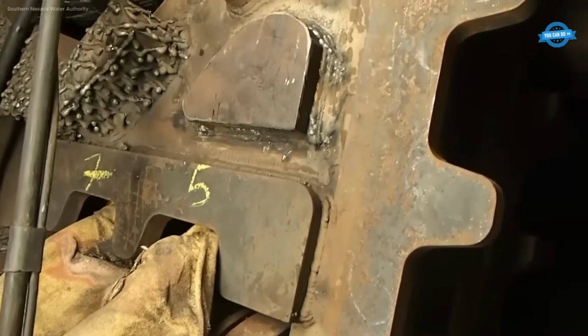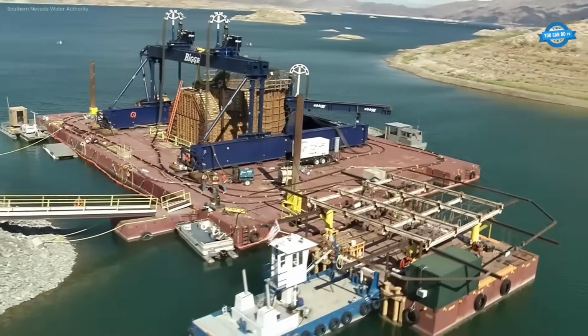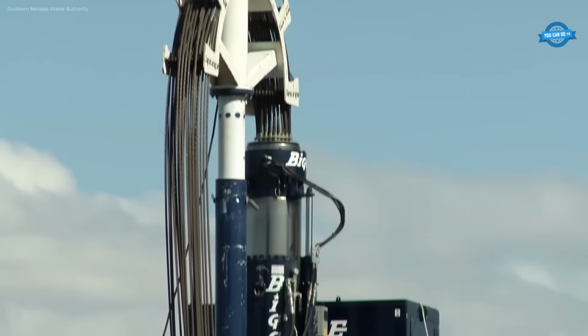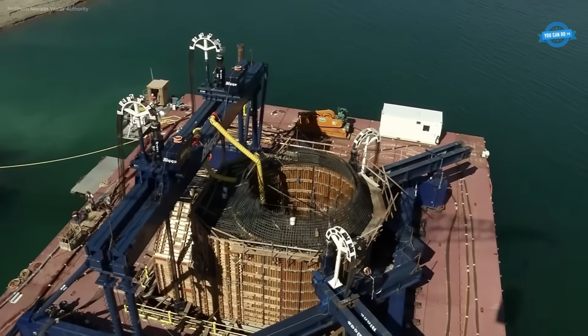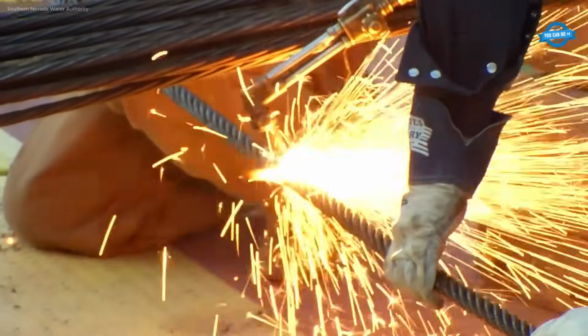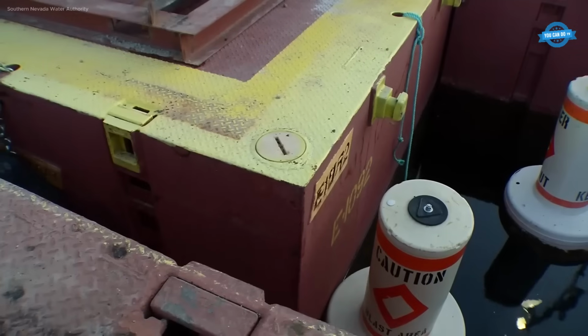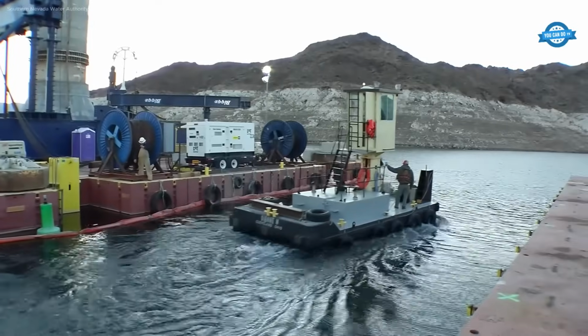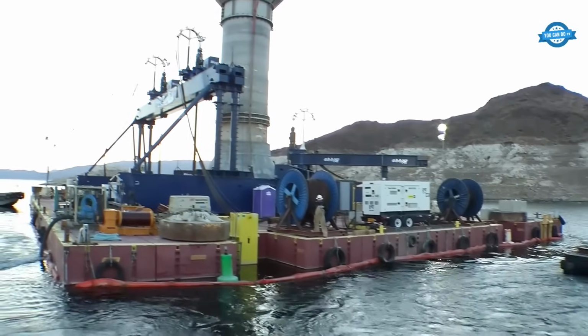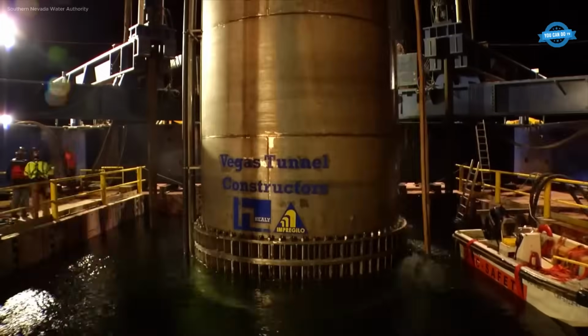Simultaneously, marine crews offshore excavated a 60-foot deep pit in the lakebed using controlled underwater blasting. The 1,400-ton intake structure was suspended from strand jacks on barges and lowered precisely. A world record underwater concrete pour followed, delivering 11,000 cubic yards of high workability mix over 11 continuous days using a 350-foot tremie system.